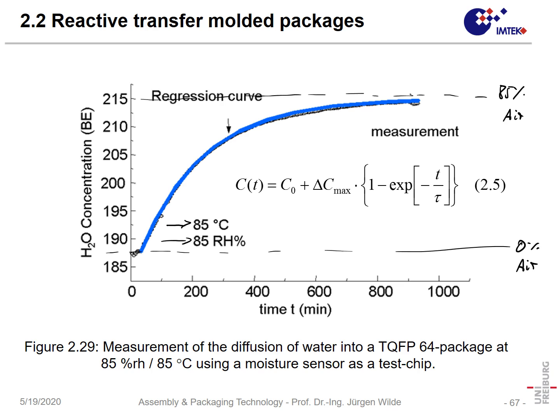When we transfer the package into the moist atmosphere, we can see after a small lag time an increase which is more or less an exponential increase. And here we can see the capacitance change over time is something like the initial capacitance plus the delta C max, which is this value, times a time-dependent function. And that time-dependent function is typically such an exponential function, 1 minus e to the power of minus t divided by tau. And tau is the time constant of our process.